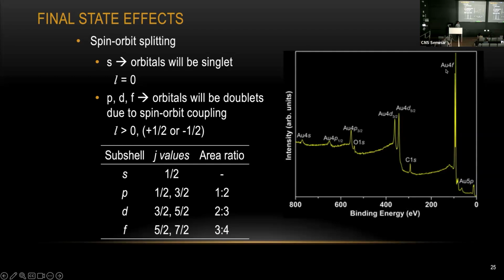So for instance, if you're looking at a gold sample right here, for the gold 4f signal, right now I can't zoom in here, but you can see a double peak right here. And all these peaks have different ratios in area underneath the signal. We will need all these numbers here for the quantification later.